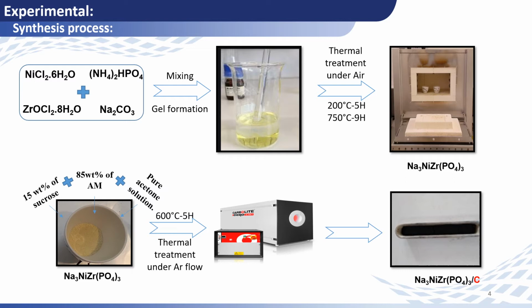As we know, phosphate-based materials have a poor electronic conductivity, so for that we proceed to a carbon coating in order to increase it. Our material was mixed with an appropriate amount of carbon source, 15% of the total weight of the material, in an acetone solution, then calcined for 5 hours at 600 degrees Celsius under a continuous flow of argon.